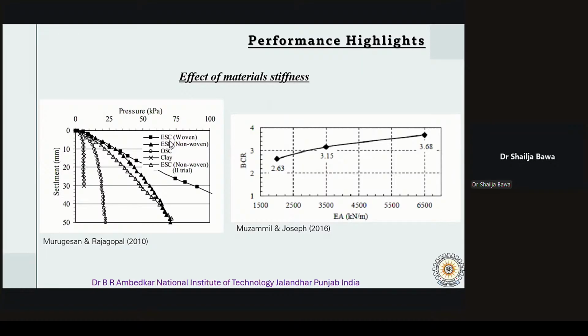and increasing resistance. So moving to the graph on the right, here you can see the bearing capacity ratio and the axial stiffness of the encasing material that has been plotted. As the EA increases, the BCR improves steadily, going from 2.63 to 3.68. This means that stiffer encasing materials allow the stone column to support a higher load with less settlement. So again, the key takeaway is stiffer encasement, better confinement, giving higher bearing capacity and lower settlement. Choosing the right encasing material can significantly improve the overall ground performance.